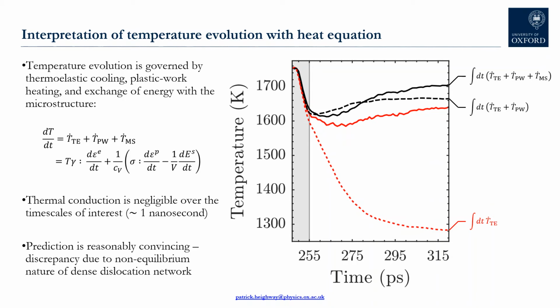Now, there is admittedly a rather conspicuous difference between the observed and predicted release paths. The 2 curves seem to drift apart between around 255 and 290 picoseconds. We think this is owed to the fact that the release rate is so rapid that our heat equation, which is based on the tacit assumption that the conditions of thermodynamic equilibrium apply, is starting to break down. This is something that we will be investigating further. However, we think the agreement is sufficiently good that we can conclude confidently that it is indeed plastic work heating that is primarily responsible for the unexpectedly high release temperature predicted by these MD simulations.